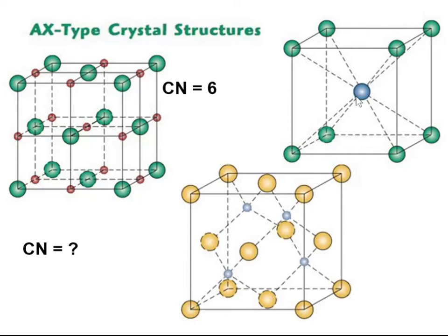This one's a lot easier to see, right? We pick this atom in the center, and it touches each corner, which is 8. Coordination of 8. And then in this structure here, if we pick this one, it's touching the corner atom and the 3 face atoms around it. This forms a tetrahedron with that in the center here, and that's a coordination of 4.